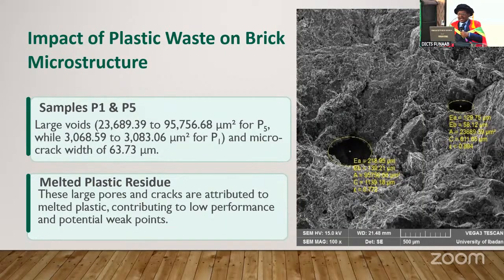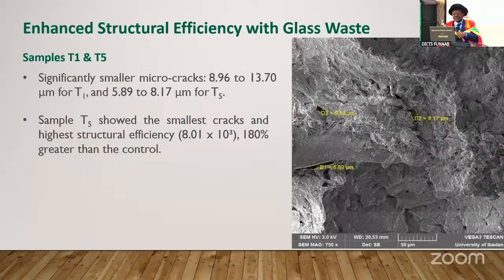These large pores and cracks are attributed to the melted plastic. When the plastic melted, it created that void, contributing to low performance and potential weak points. Now, for the glass-infused bricks, for T1 and T5, significantly smaller microcracks were observed between 8.96 to 13.70 micrometer for T1 and between 5.89 to 8.17 micrometer for T5. Sample T5 showed the smallest cracks and the highest structural efficiency of 8.01, 180% greater than the control.